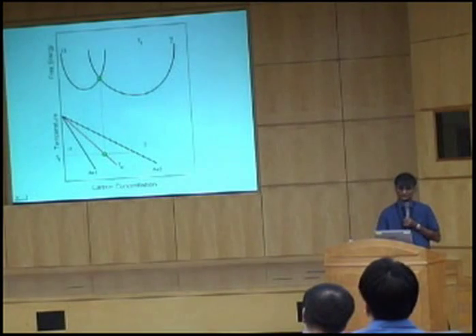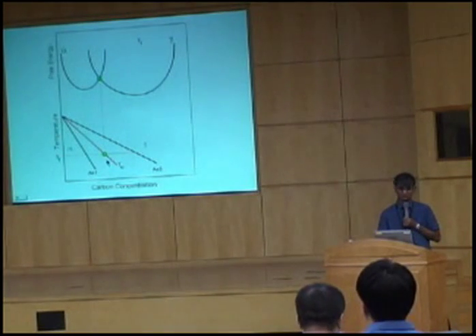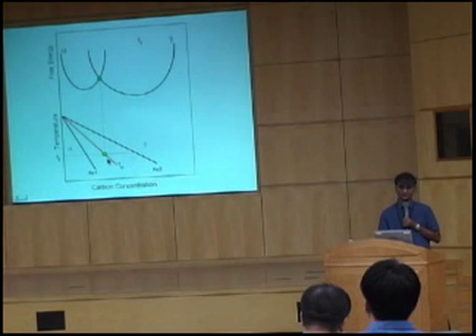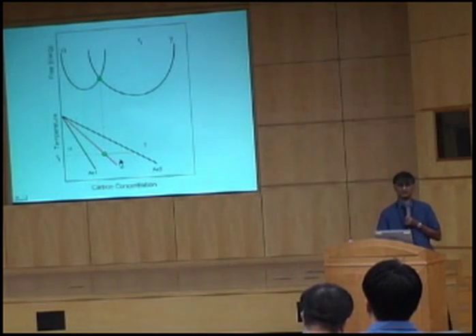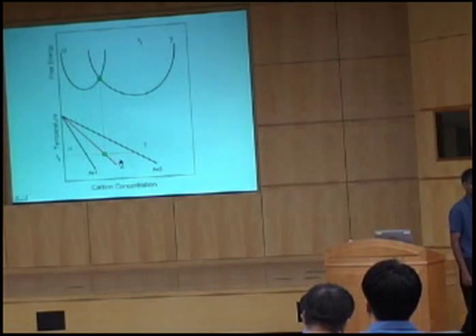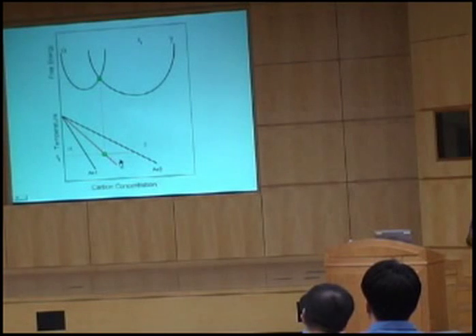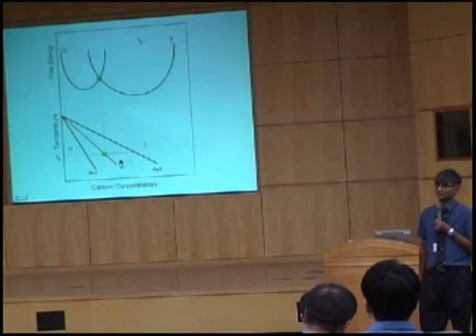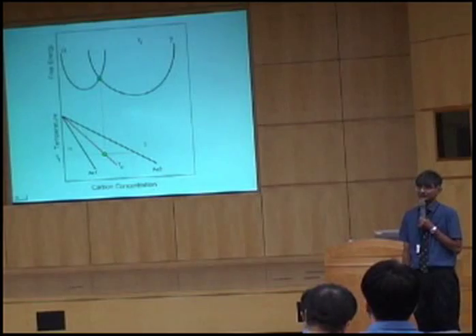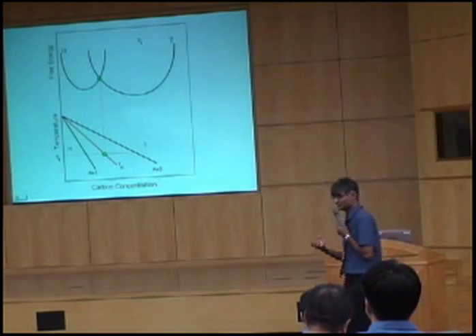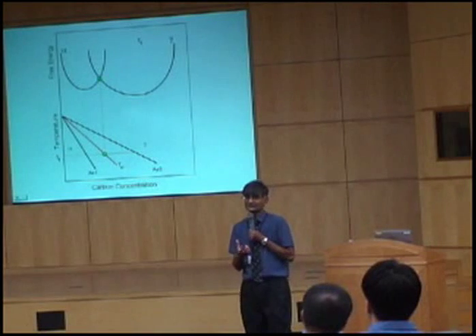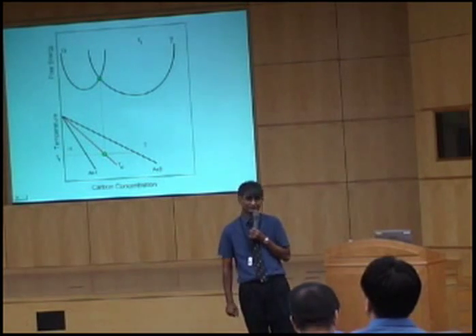Okay? This is the curve that I explained to you yesterday. Once the austenite reaches this carbon concentration, it is impossible for it to transform into bainite. Yeah? Thermodynamically impossible to transform into more bainite. So we have a big problem that we want to get rid of these large islands of austenite, but thermodynamics tells us you cannot do that.